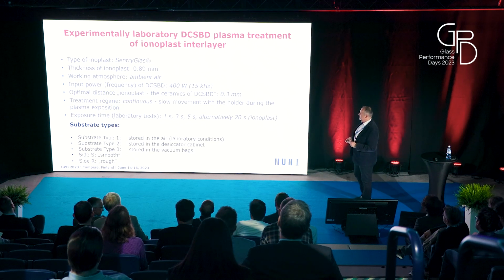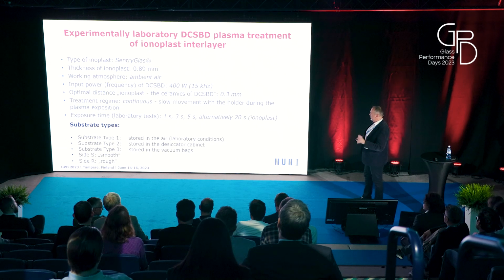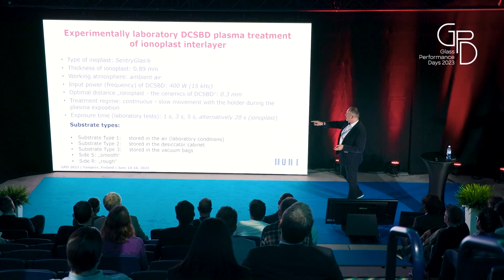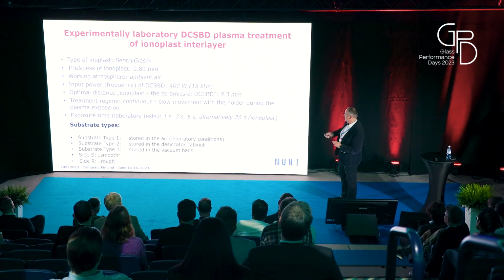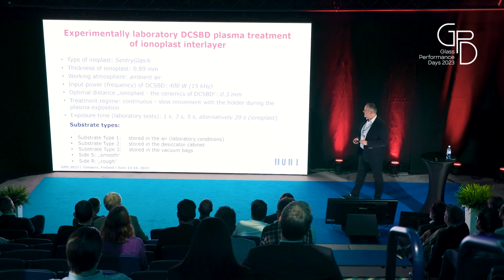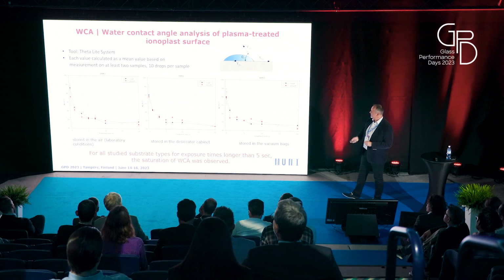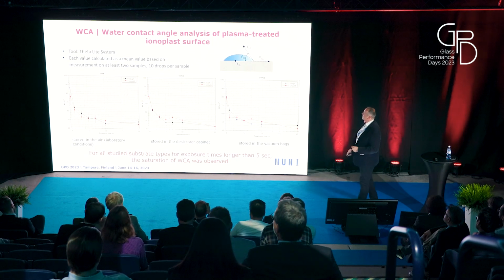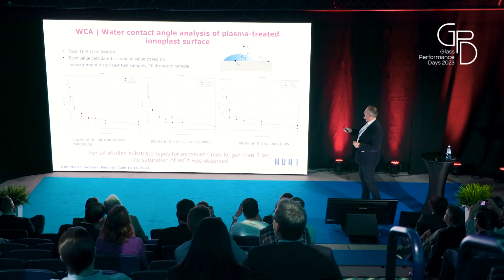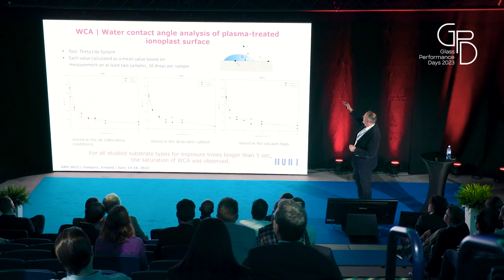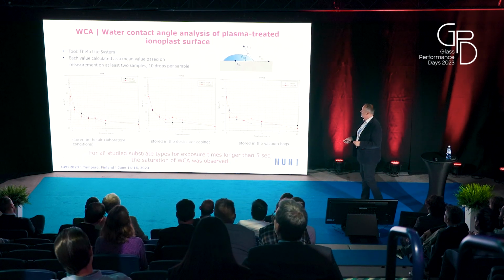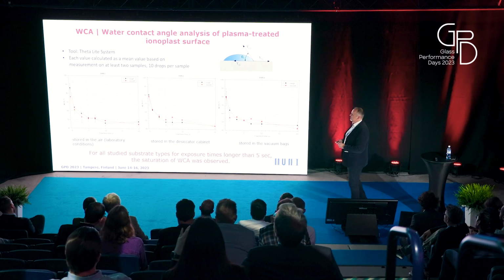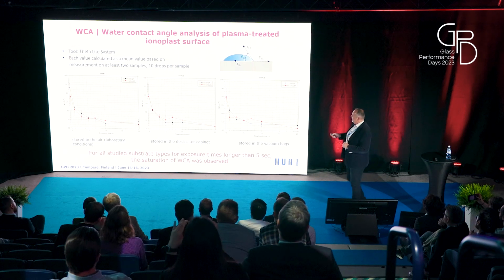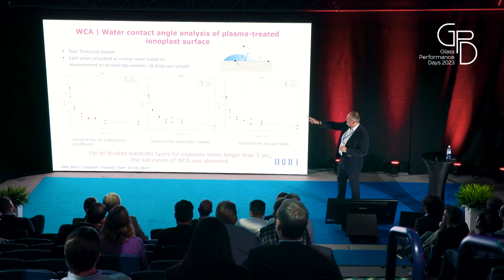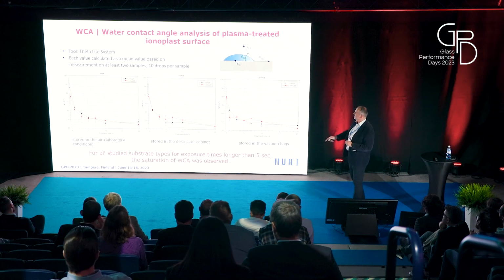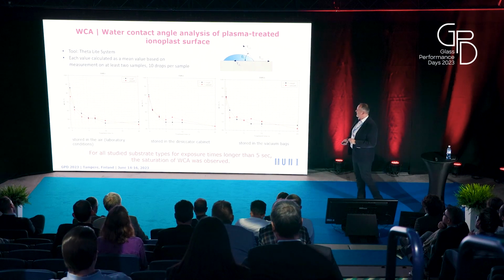We know that it is very important to store the ionoplast in good conditions to prevent humidity. So we investigated different samples which were stored in the air, stored in a desiccator cabinet, and stored in vacuum bags. We investigated, as a simple method, water contact angle measurement. As you can see, it is the angle between the interface of solid and liquid, and between liquid and gas phase. If this angle is lower than 90 degrees, we can consider the material more hydrophilic. As you can see on our graphs, even after a very short exposure time, of 1 second, we were able to reduce the contact angle significantly.